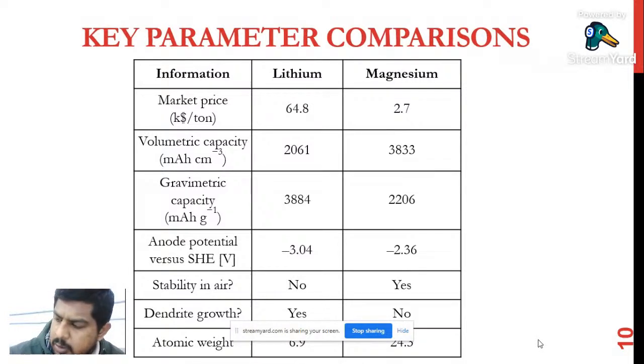Then when you are going for a battery, we have to compare these key parameters. One is price. Lithium is something like 64.8 thousand dollars per ton. But when you compare with magnesium, it is only 2.7. The volume capacity, when you compare with lithium, is a little more. But the gravimetric capacity is low, something like 2206 compared with lithium. This is because the atomic weight is higher for magnesium, so it is heavier than lithium, and the value gets reduced. But it is an alternative material which is nearer to lithium.